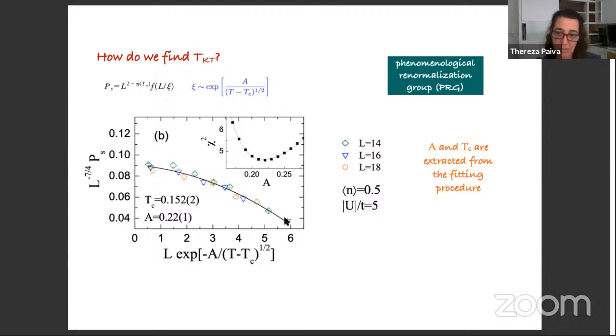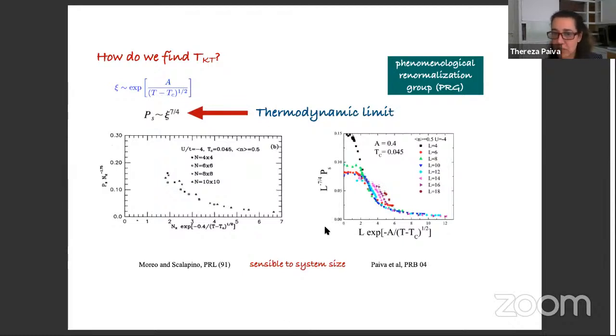And this plot has been done by Nathanael, and he was really careful to change A. This is a fitting parameter A, and the temperature is also extracted from the fitting. And here, at the point where we have the smaller chi is the A we take, and then we extract the temperature. The thing with this kind of fitting is that it is very sensitive to system size. So this expression here only holds in the thermodynamic limit. And so in early calculations, when only smaller system sizes were available, there seemed to be a collapse for some given values of TC and A.